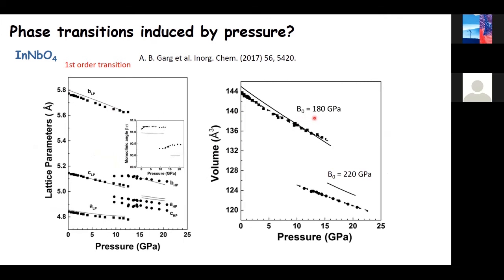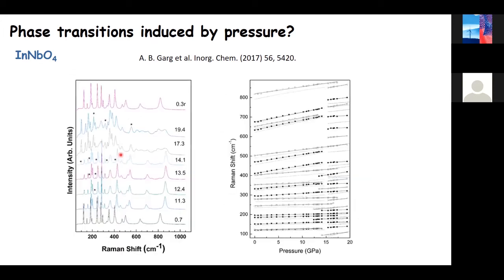As in indium niobate, the bulk modulus of the low pressure phase is close to 180, and the one in the high pressure phase is a little bit about 220. So all these changes, in particular the drastic changes at this phase transition, should have important consequences in the electronic properties.